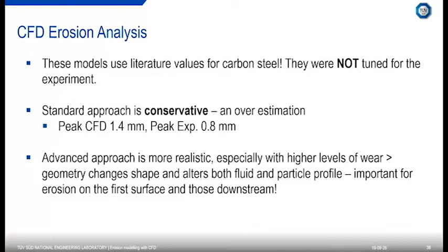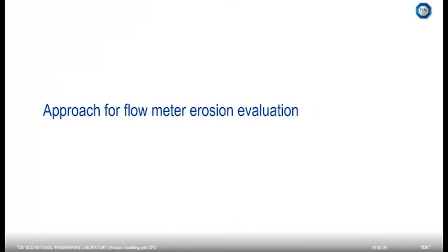The advanced approach, however, is more realistic, especially with higher levels of wear. It changes the shape of the geometry. It alters both the fluid and the particle profile, and it's important for erosion on the first surface and also those downstream. So we had a peak of 0.9 against 0.8. Excellent. Good. So I think we are at a stage where we now understand the majority of components that go into how we model erosion.